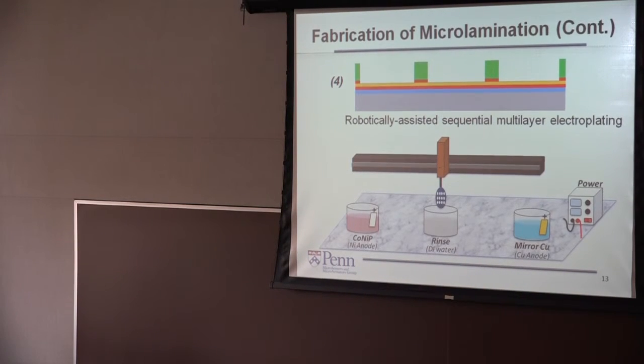And basically, after that, you remove the tie seed layer, and then you have a traditional electroplating. But we utilize a robotic controlled system to do the multi-layer electroplating. So we use the cobalt nickel phosphor bath, which we customized to optimize the property, and the mirror copper bath, as we talk about. So I'll show you a video about this process.